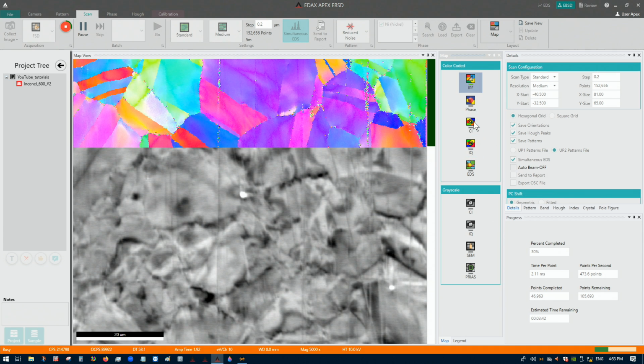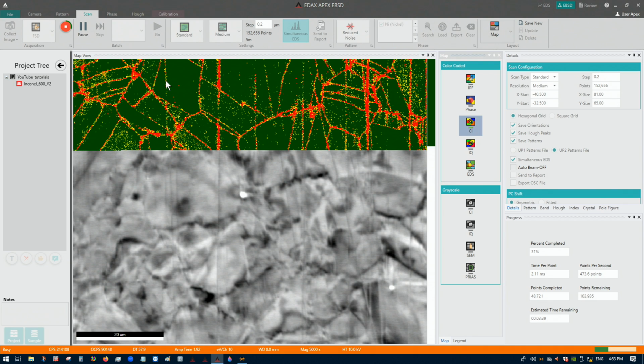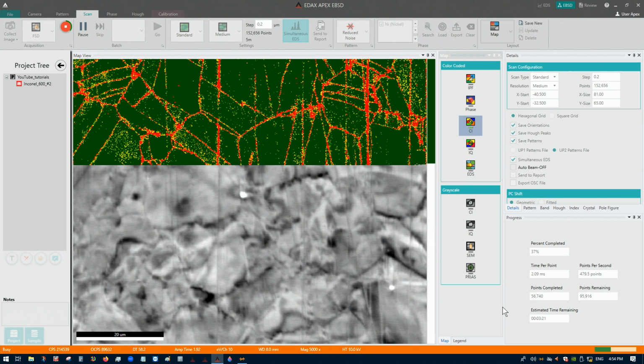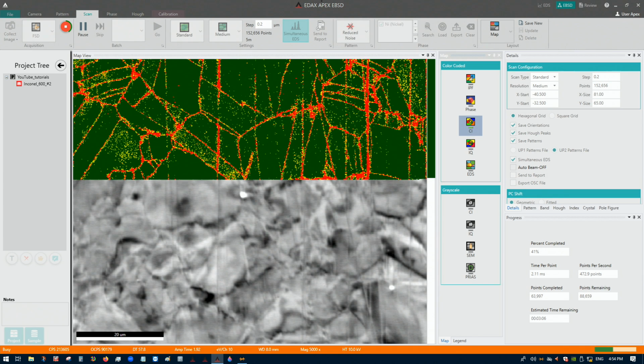Okay, confidence index. So this is a measure of how confident the system is in its solution. So green is high confidence and red is poor confidence. So we can see where we have grain boundaries and/or scratches, our confidence is not as high, which is understandable. So it looked like actually the spot where I selected the scratches were a little high there, but that's okay. Again, the goal here isn't to show off my awesome polishing skills, but just to show you how to use Apex, okay?